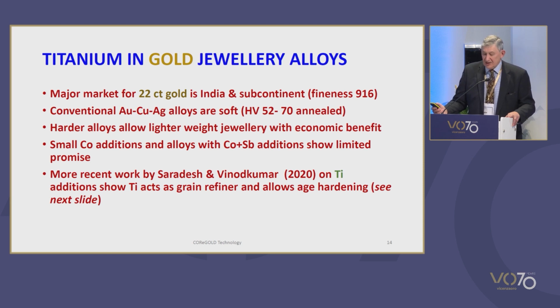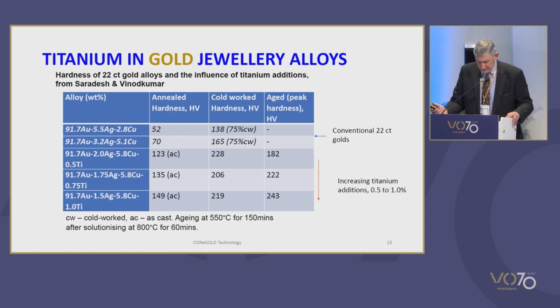But more recent work by Saradesh and his colleagues on additions of titanium to 22 carat gold have demonstrated that titanium additions act as a grain refiner and allow substantial age hardening. Some results are shown in this next table. And we can see, compared to normal 22 carat golds, additions of 0.5, 0.75 and 1% titanium. And we can see in the annealed, in the cold work and in the aged conditions, we get considerably higher hardnesses. And for hardness, you can read strength as well.